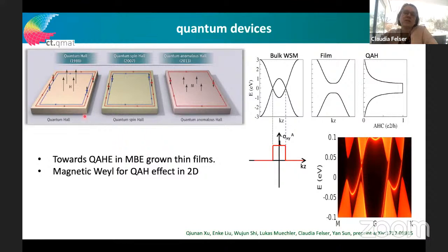And I'm sure you heard about the quantum Hall effect in the context of the discovery of von Klitzing. So you have also these topological two-dimensional edge states in a big magnetic field at low temperature in a two-dimensional electron gas. So if you destroy the sample here, also here, you cannot destroy the spin current around the sample. And the quantum spin Hall effect even shows this effect without an external magnetic field, and this was discovered by Molenkamp in mercury telluride. And if you have a magnetic material, you suppress one of these topological edge currents, and you can have a quantum anomalous Hall effect.